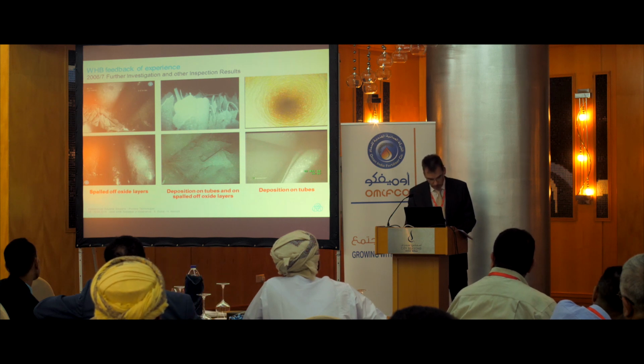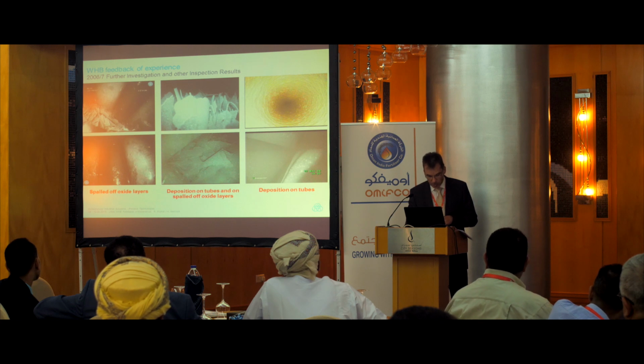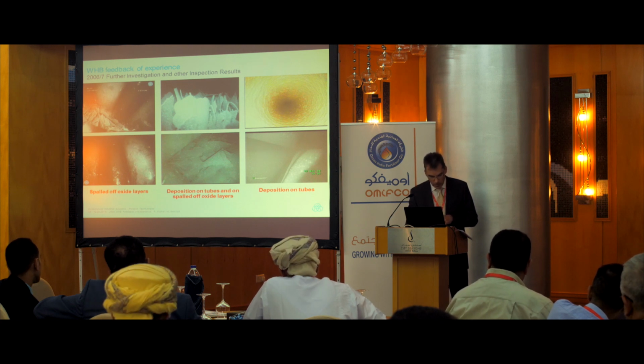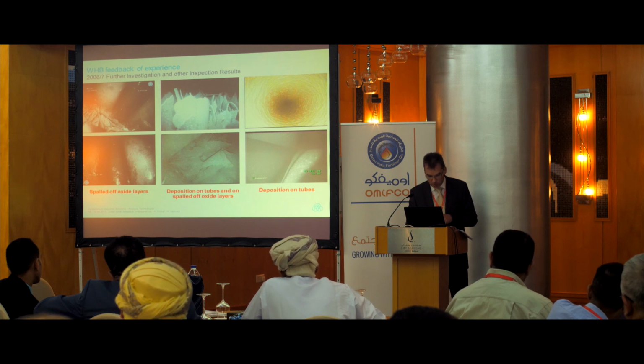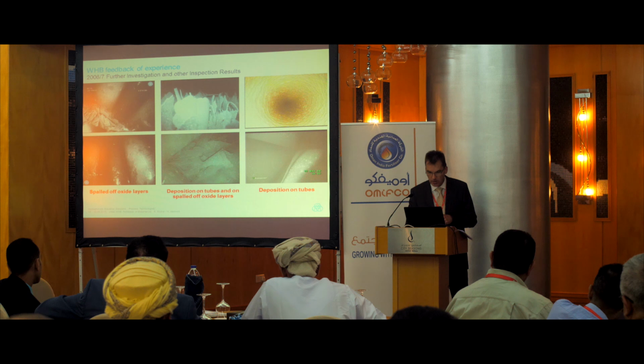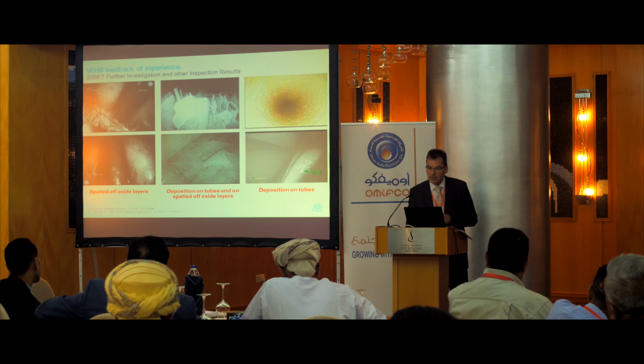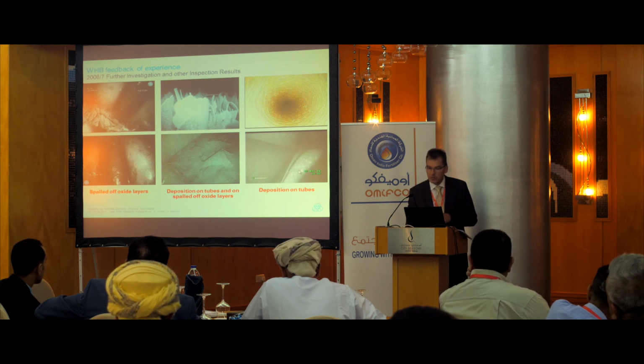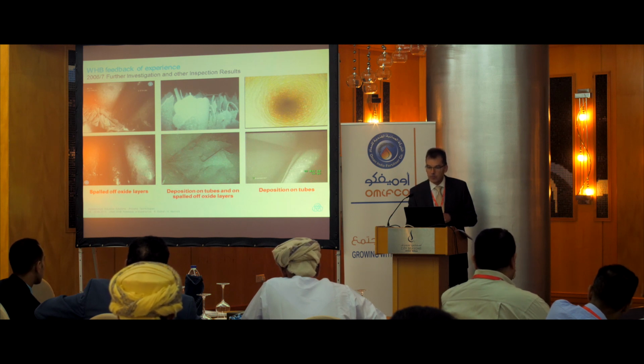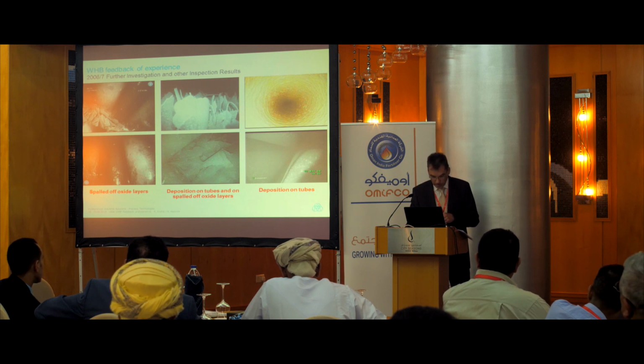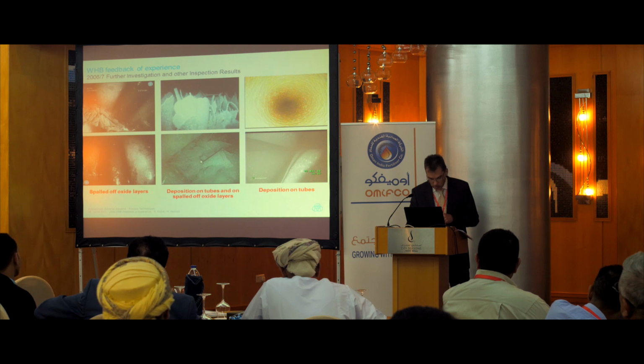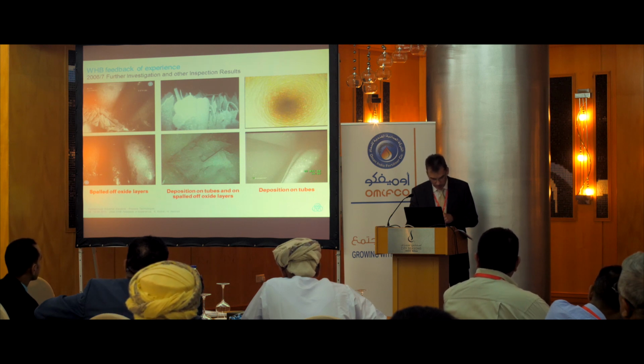Second source, porous oxide layers can also be formed by deposition on tubes and other iron parts, where dissolved iron in the liquid gets deposited on porous magnetite, which appears as a sparkling surface. When this happens and you go with the borescope to look inside the boiler, you see some sparkling effect. This is due to the light of the borescope, of course, but this is an indication that something is wrong with the boiler feed water. Some iron is in the boiler feed water, which will be deposited. Also, a combination of both effects is possible, as seen in the center photo. The two photos showed spalled off oxide layers, here and here, with additional deposition of magnetite on these oxide layers.